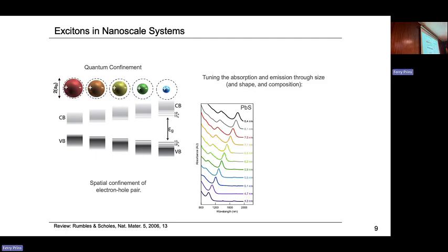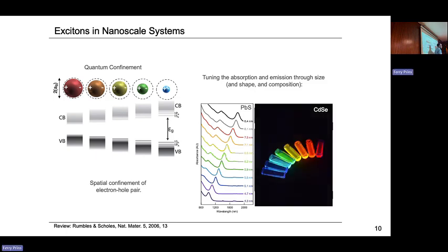This is very interesting for applications. If you have a light emitting application, then in the case of cadmium selenide, you can see it's visible—you start off with red in the bulk and you go to the blue. Then you can choose your LED color or your TV screen color simply by shifting the size of the particle, within the same chemistry, if you can control the size.